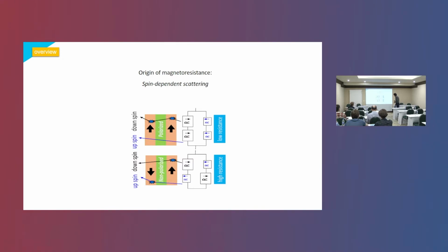So this is messed up, I didn't mean this, but then we can see this. The magnetoresistance, in essence, is because of spin-dependent scattering. When all the spins are aligned, scattering will be largely reduced, therefore we have negative magnetoresistance. So this is the essence of negative magnetoresistance.